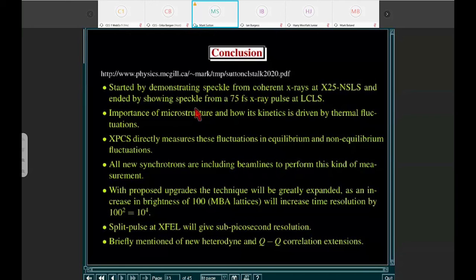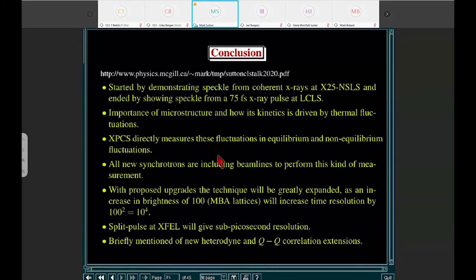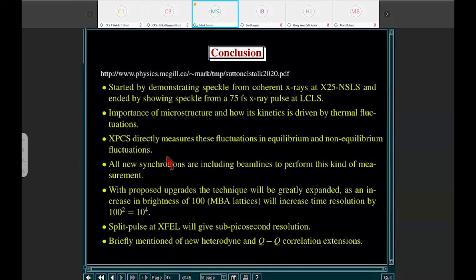I wanted to emphasize again the importance of microstructure and heterogeneity in kinetics and how that is driven by thermal fluctuations and how XPCS can directly measure this kind of stuff. And we can do it both in equilibrium and in non-equilibrium systems. All the new synchrotrons being built should have an XPCS beamline, and there's lots of opportunity there. The opportunity for small angle XPCS is fairly well exploited by the current set of beamlines. To me, the most interesting thing is that just like wide angle X-ray diffraction has more information about the structure of materials than small angle scattering, wide angle XPCS has much more information than the small angle XPCS that I've mostly shown you so far. The coherence conditions are more stringent the higher the angles you go, but we're now getting beams that are coherent enough to do that.